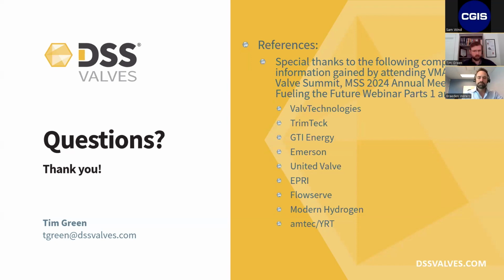Now the spring is if you've got water hammer as a concern. Hammer being the reverse flow, causing that disc to slam closed and create a shock wave in the line. That's when a spring really helps, to get the disc closed rapidly and prevent hammer. But if that's not a concern and you want a valve that opens very easily under very low velocity, we talked about sizing. When we're at 6 to 7 feet per second of water with a spring, if you get rid of the spring, it cuts that in half, so it's around 3 feet per second. It allows the valve to open easier as well. So unless water hammer is a concern, I would recommend in a lot of cases getting rid of the spring.